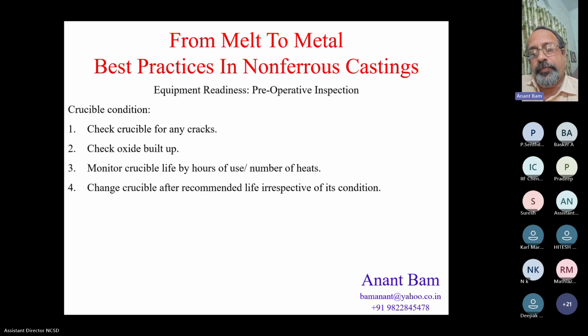Crucible condition. Before starting, check the crucible for any cracks. Check for oxide buildup. And it's a frequent check or routine check. All the checks are daily checks or every heat-wise checks. Before you put in any new material, check the crucible condition, check the oxide buildup, check the thermocouples, oxide buildup on the thermocouples, check other equipment like ladles, spoons, or any hand tools. All the checks are routine and daily checks. There is no escape to it.